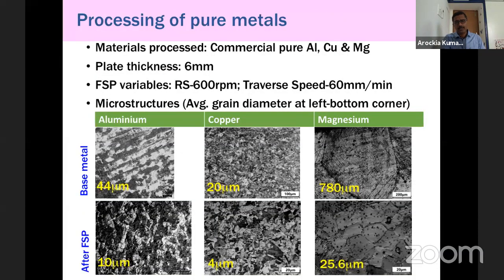What I'm showing here is that in pure aluminium, we were able to decrease the grain size from 44 to 10 micron after FSP. In copper, 20 to 4 micron. In magnesium, it is 780 to 25.6 micron. So the grain size was very coarse in the as-received material, but it is greatly refined after FSP. Then how does this influence the damping property of the material?